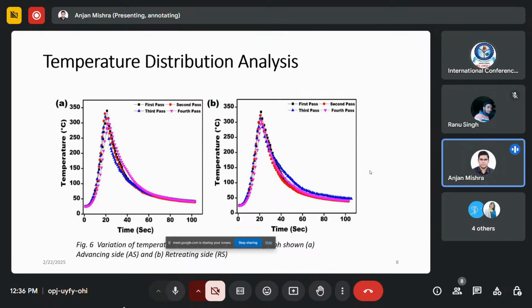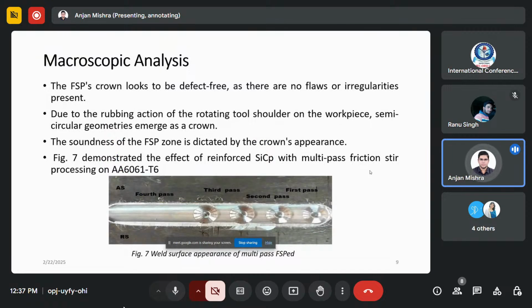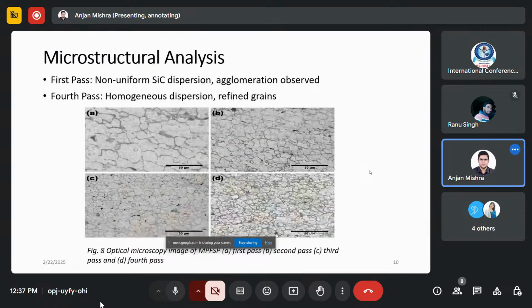The advancing side is showing higher temperature as compared to the retreating side, and as you can see, as we increase the passes, the peak temperature is decreasing. Now, in the macroscopic analysis, as you can see in the image, there are 4 passes, and you can see clearly the rubbing action of the rotating tool shoulder on the workpiece, creating a semicircular geometry that emerges as a crown. It is known as a crown, and it is showing no flaws and irregularities in this present experiment. For microstructure analysis, we have used optical microscopy analysis.